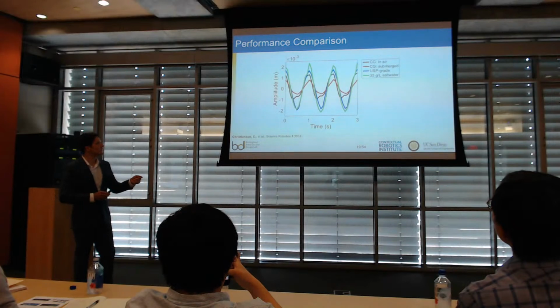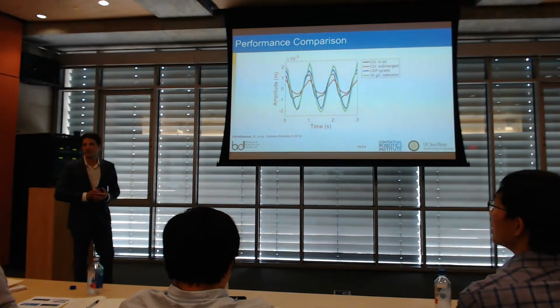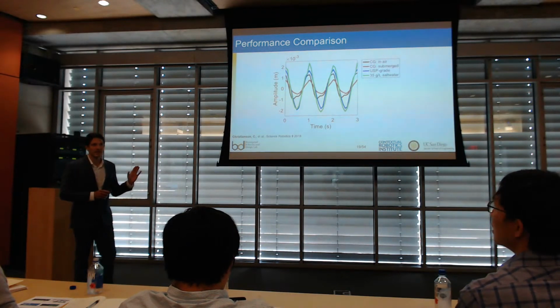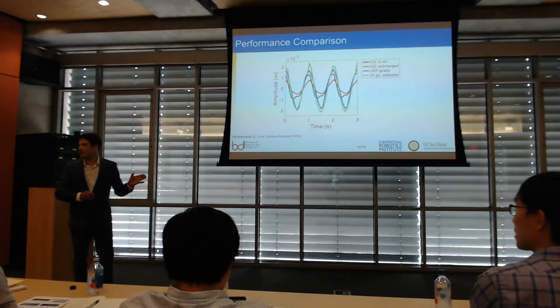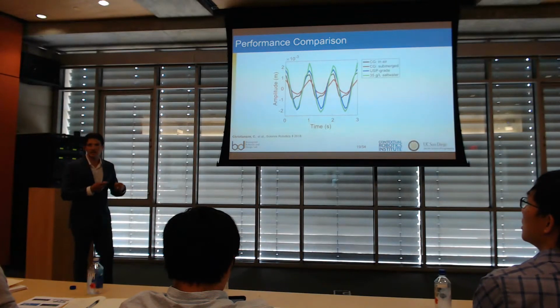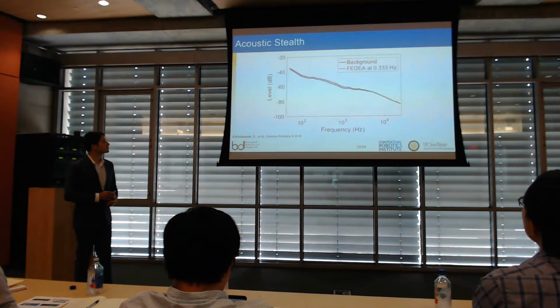And so in green, we have very salty water, and you can get the most actuation performance from it. But then we also tested it with pure water, and we can still see some actuation from it. And so for our test, to simplify some of the manufacturing, we just use deionized water as a starting water, instead of making salt water every time.